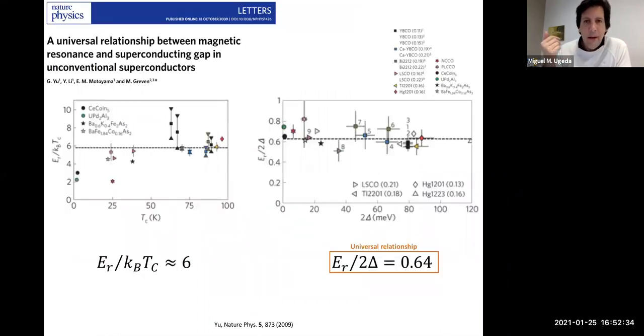So there is a work that attempts to create a link between these magnetic resonances and the existence of the superconducting gap, the strength of the superconducting gap. And these guys discovered that there is a well-defined, universal relationship between this omega, or this magnetic resonance energy modes, and the absolute gap, the magnitude of the gap. And that universal relationship follows this ratio.